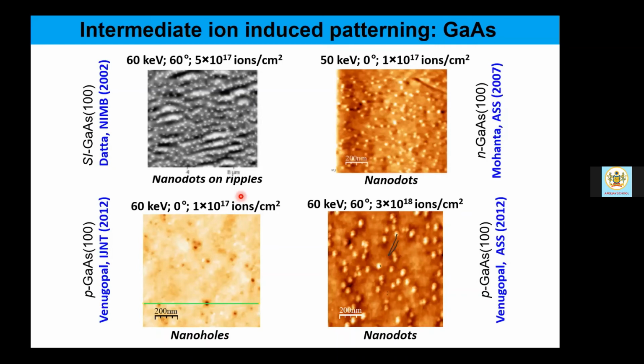So in those cases, mostly the lighter mass atomic species get preferentially sputtered more. Preferential sputtering means that will be preferred to get sputtered fast ahead of the other heavy mass element present in the same target. That means the other component or atomic species. Now this is very different for gallium arsenide. Here, the preferential sputtering is almost absent because gallium and arsenic both have nearly similar sputtering rate.